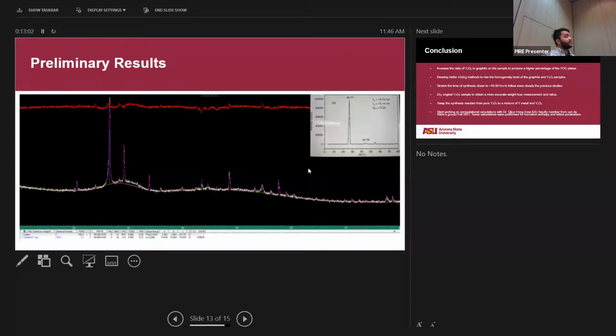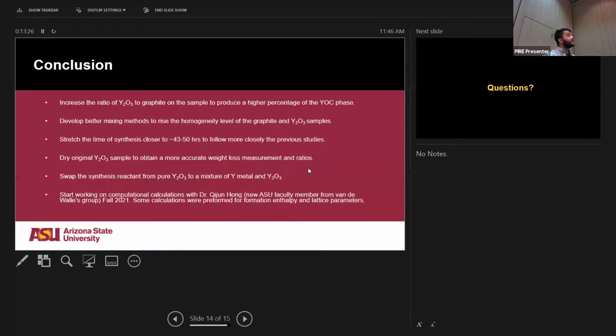Here is the one afterwards, and I added the graphite XRD spectrum so you could see where the peak is supposed to be. And here we have a 95 to 5% difference, which led us to a conclusion that we need to develop better mixing methods for our powder. We're still in the discussion to see what we can do about that.